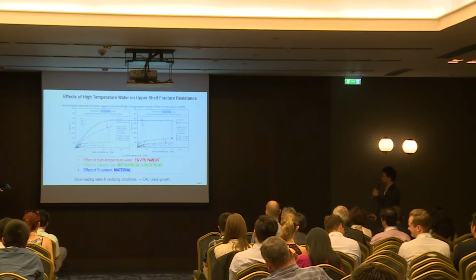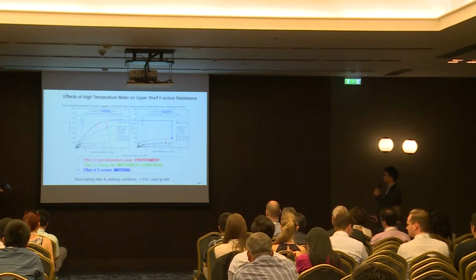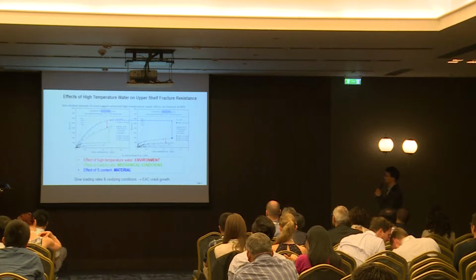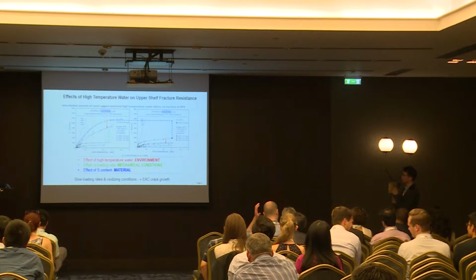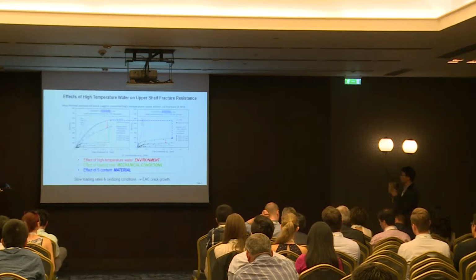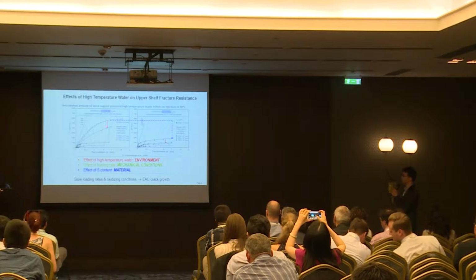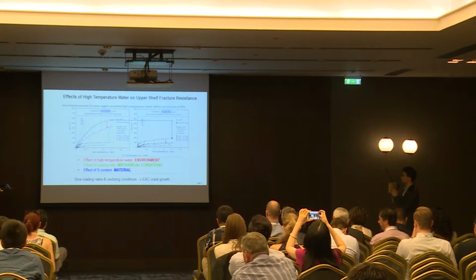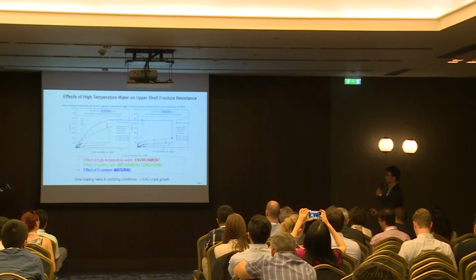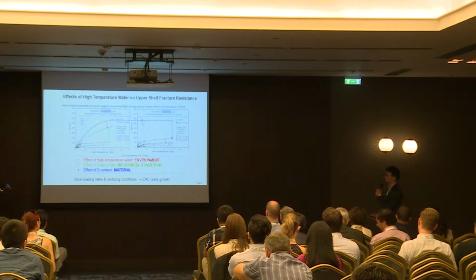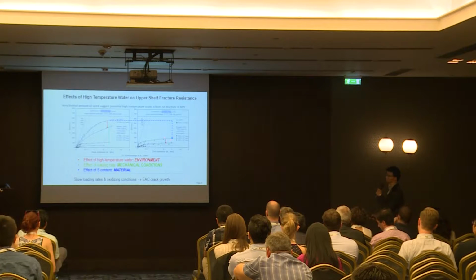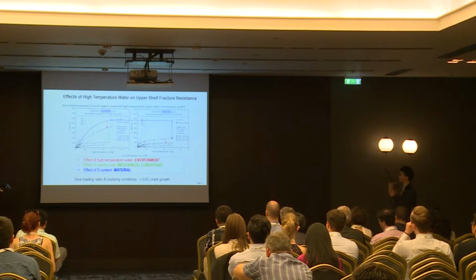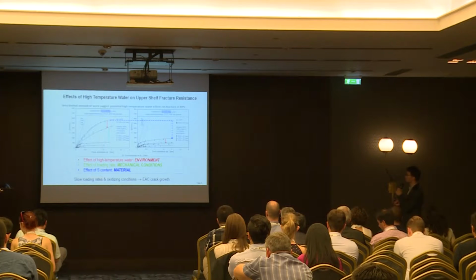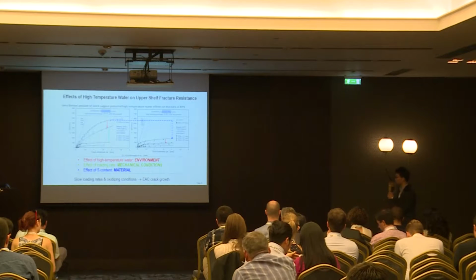And this curve with square symbol was the test conducted in air, and the other three lines were the tests conducted in the same high temperature water environment, but with different loading rates. And these red arrows indicate the environmental degradation from the high temperature water, as a reduction from the test in air. And the green one indicates the effect of the loading rate, so it's the mechanical conditions. And if we compare the two figures, we see that the test in air also has a reduction when there's a higher sulfur content. So it means basically when we're discussing high temperature water effects, the environment, mechanical conditions and materials all need to be taken into consideration.